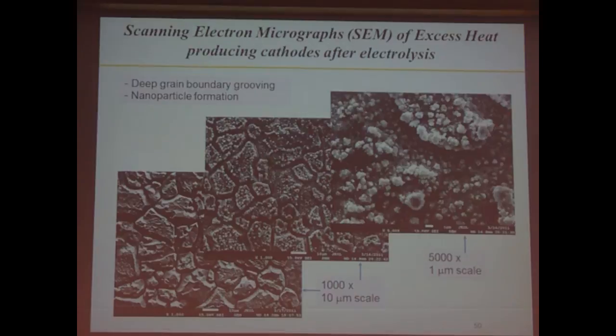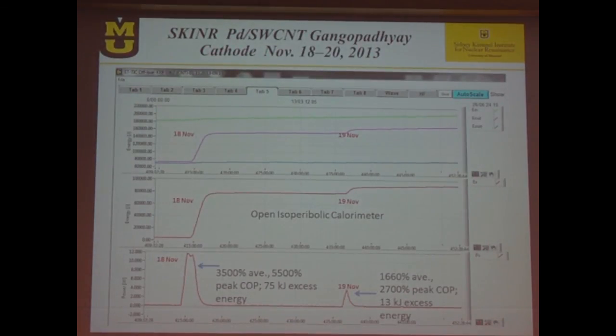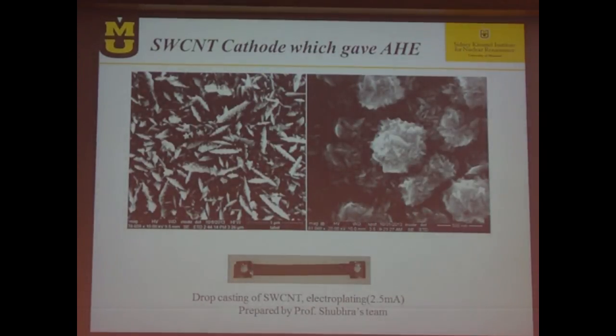where is the voltage? I don't see it now, but the voltage went up to 12 volts. And as we touched it, immediately the voltage collapsed back to 2.7 volts, which is the typical voltage when there is no excess heat. Now, what we believe happened is we had this resonance that I'm talking about, and that built a capacitance inside the cell, and the moment we touched the poles, we collapsed. The impedance was changed back to the initial conditions. This is why we believe that resonance is very important, and we have to excite the lattice at high frequencies, and that will increase the probability for excess heat.